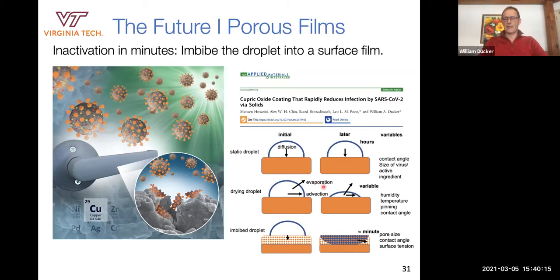It depends on humidity. So the solution is to imbibe the droplet into a porous film. So as soon as you imbibe it in there, first of all, you've got a lot more area of active ingredient. But the main thing is now the diffusion length is the size of the porosity. So if we make this porosity on the scale of microns, well, then diffusion takes only minutes. So a porous film is the way to go.